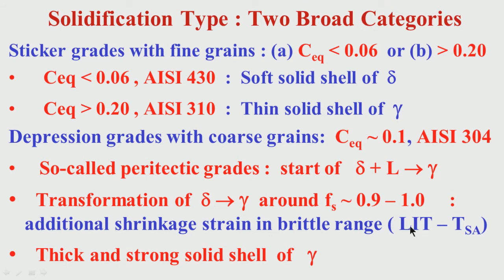So, what is happening here? Along with that, this transformation is delta to gamma, as I have mentioned. This is around the most brittle temperature region, solid fraction 0.9 to 1. So, there is additional shrinkage strain in the brittle range. This shrinkage from this transformation is adding to normal shrinkage in this brittle range between LIT, liquid impenetrable temperature, and actual solidus. LIT corresponds to solid fraction of 0.9. Actual solidus corresponds to solid fraction of 1.